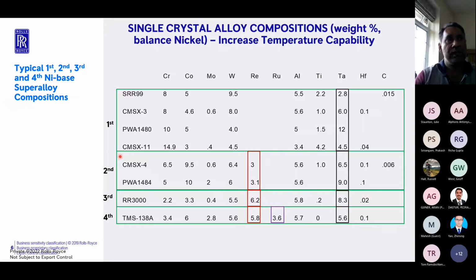So if you look at the alloys that one can use to develop the temperature capability, looking at nickel base alloys, so now we're looking at the turbine, you can track the evolution of these alloys roughly over 4 generations. Now, again, I'm just mainly focusing on single crystal alloys. If you look at the whole gamut of nickel base alloys, you can start off with equiaxed alloys and then directionally solidified alloys, both of them being polycrystalline, and then single crystal. But practically every component in the turbine, apart from the LP, LP being low pressure, is single crystal. So the onus will be now on single crystal.